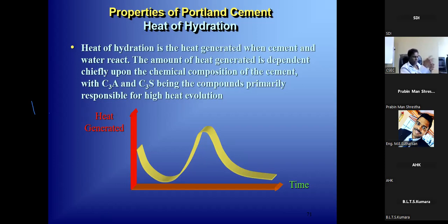Different places try to do that, but this is what I've been following forever. And I have even had PhD students working on this area. But that is there to reduce the cracking, because excess heat will generate some smaller cracks within the concrete. So to avoid that, we put limits, like now, to reduce to 70 degrees.